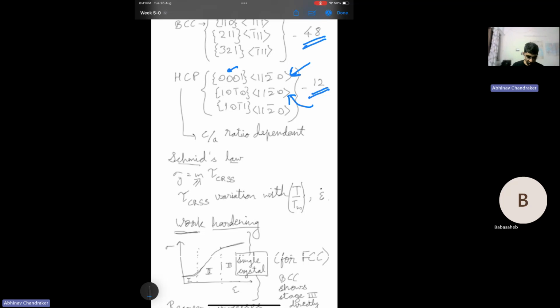We have already looked at resolved shear stresses, so it can also be written in this form, where sigma y, here we are looking at yielding phenomena. If the applied uniaxial stress leads to yielding, then it can be called sigma y, the yield stress. In that case, the resolved shear stress value can be considered as a critical resolved shear stress, because that is the resolved shear stress value at which the material is plastically deforming. Since we know that loading above yield strength will cause plastic deformation, we can relate that to the resolved shear stress on a slip system and call it the critical resolved shear stress.